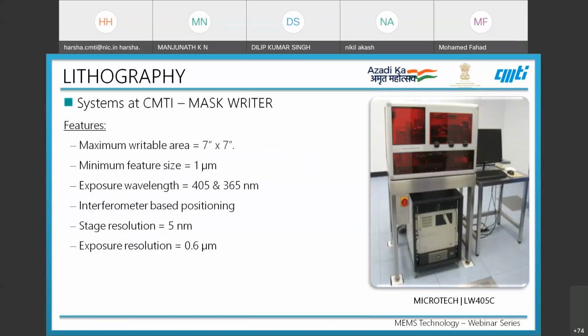For direct to wafer writing, we can also use a mask writer. We have a mask writer from Microtech, which has a maximum writable area of about 7 by 7 inches with a minimum feature size of 1 micron. We have two different wavelengths, 405 and 365 nanometers, and interferometer-based positioning for higher accuracy. The stage resolution is about 5 nanometers with an exposure resolution of 0.6 microns.